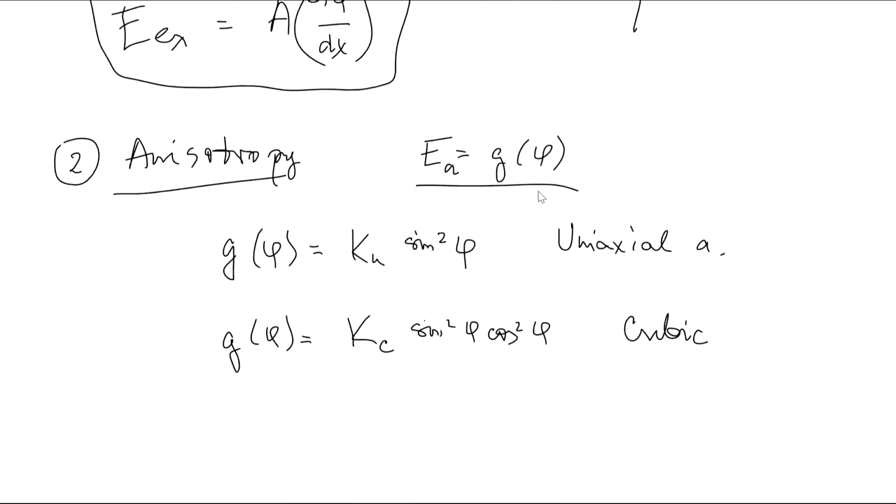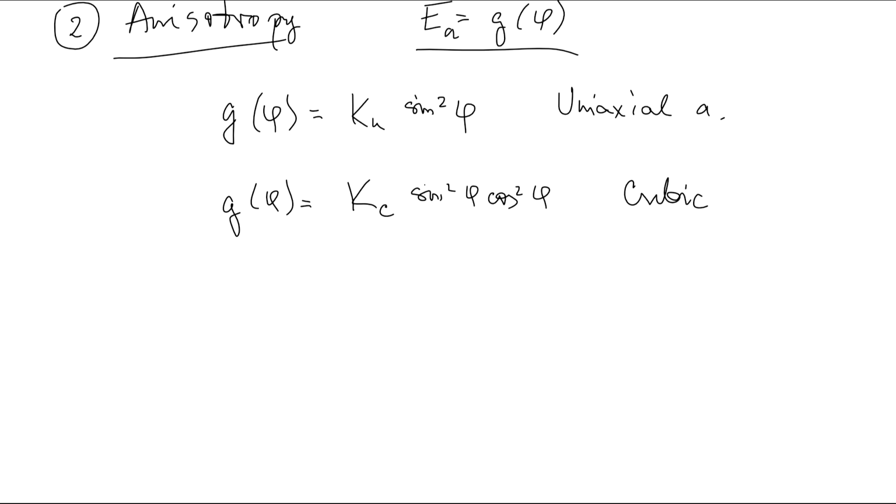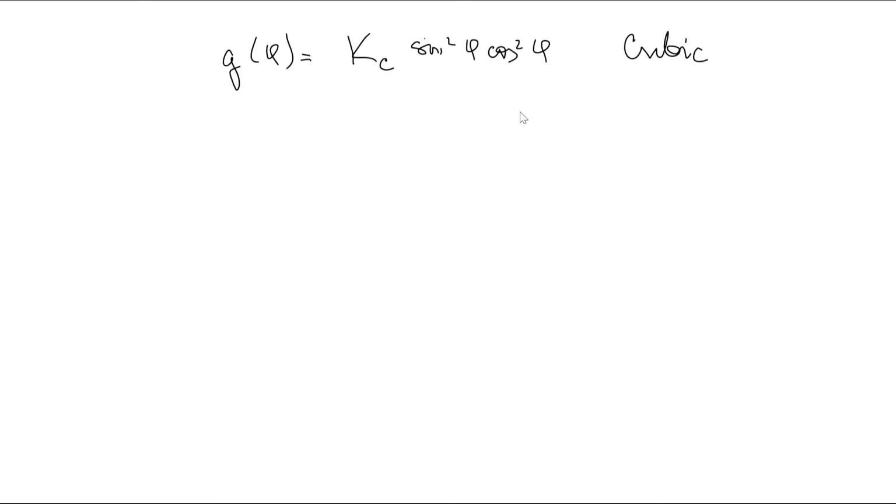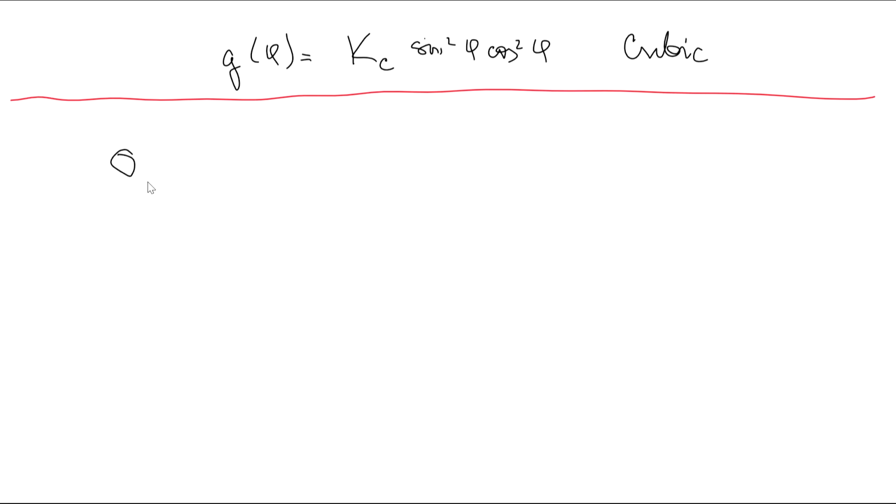Now let's scroll to where we are. And this is the expression. Okay, so from this we can look at the energy stored in the domain wall. We can talk about domain walls, but typically let's talk about the surface energy, because a domain wall is a surface between two areas with different domains. For the surface energy, I'll use sigma, and it's energy per surface, which would be comprised of exchange energy and anisotropy energy. To calculate that, we basically have to integrate over the material.